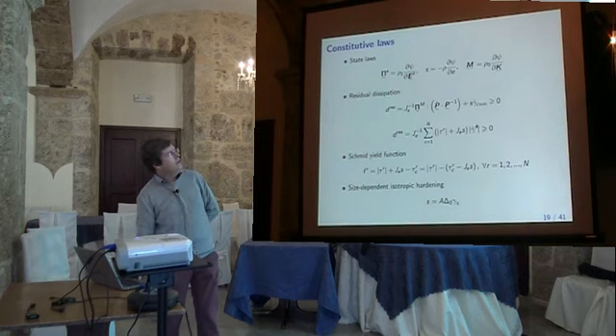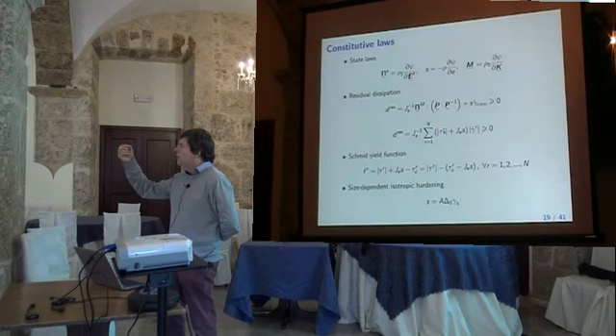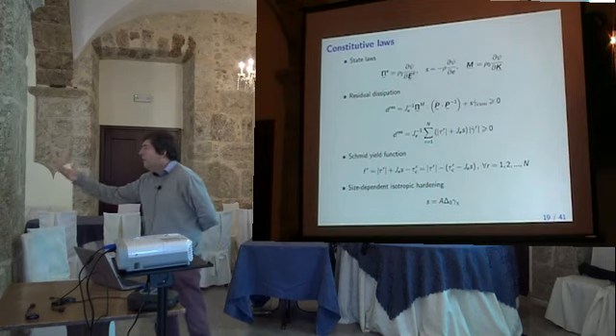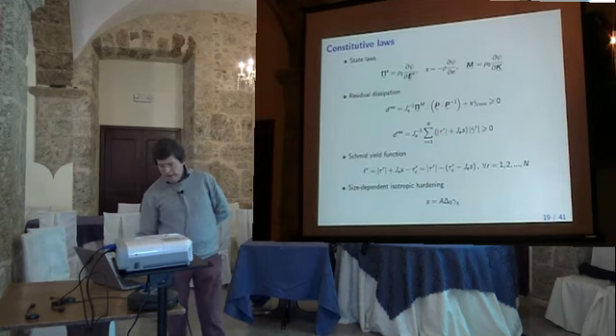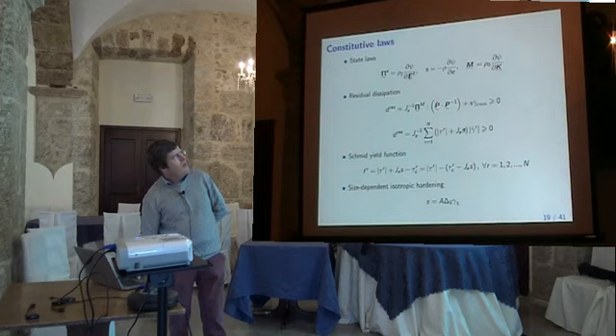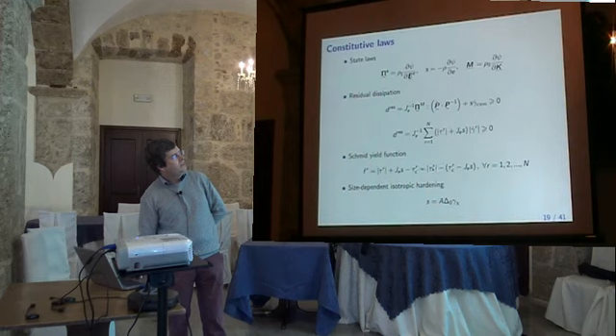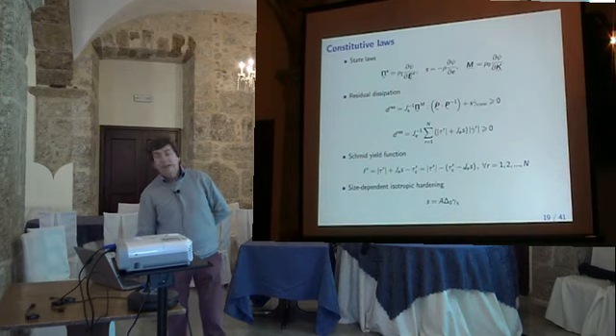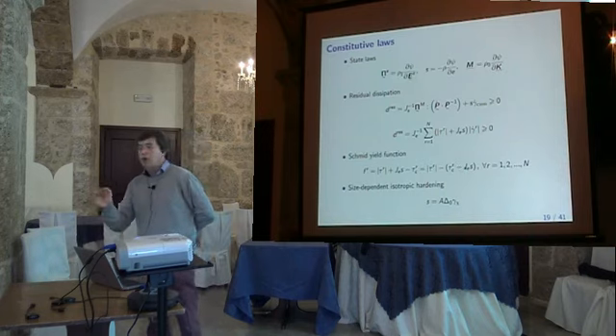Because if you see that and you want the dissipation to be positive, you are entitled to modify the usual Schmid law, which says that the shear stress is reaching a critical value, which is a yield strength, if you want, yield stress, sorry. But we modify it in the way that we introduce also this. This is our new criterion, so you can interpret it like this. There will be plasticity when the resolved shear stress is higher than the critical resolved shear stress, corrected by this higher order stress, which comes in here.